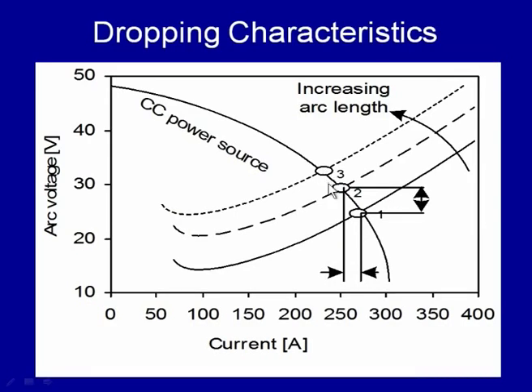Similarly, a further increase in the arc length will shift the operating point from 2 to 3, and this will also increase the arc voltage without decreasing the welding current significantly. So, this is the advantage of the constant current type of power source. Depending upon the slope, there can be different dropping characteristics of the power source. It is always desired that a greater change in the arc voltage results in a smaller change in the welding current.